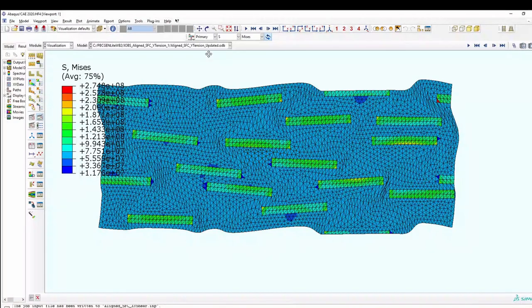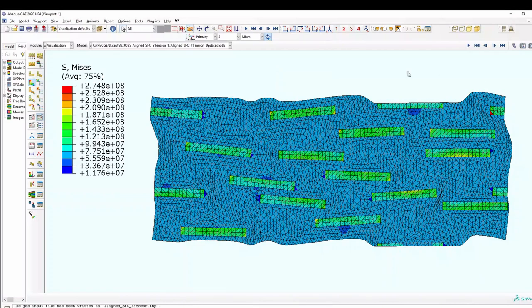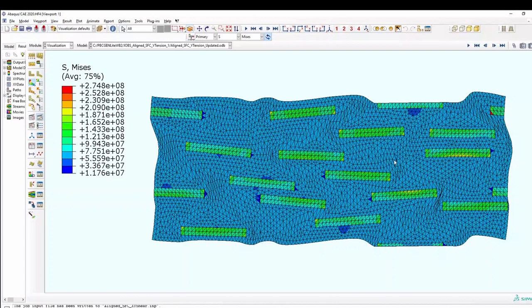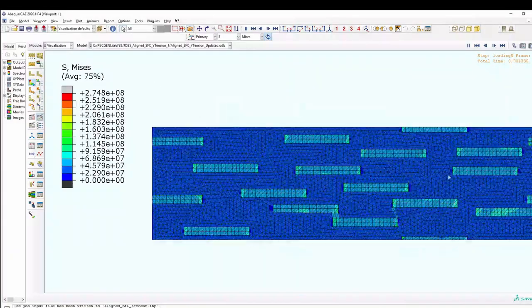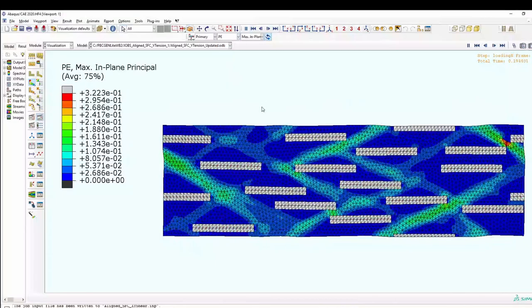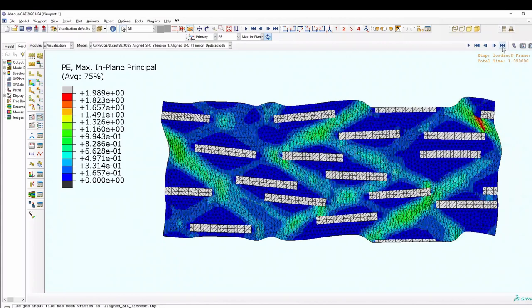Looking at the Y-tension case, we get a similar kind of behavior but more interesting. There is clear evidence of periodicity in the domain — the fibers are bending and adjusting their positions due to the transverse loading, with some seeing compression and some seeing tensile deformation. Animating shows the domain being pulled in the Y direction and compressing accordingly. The plastic strain shows clear formation of shear bands across the material as load is redistributed — a nice distribution showing how this system behaves in Y tension.